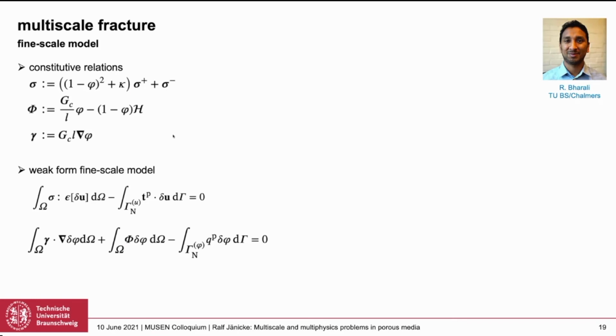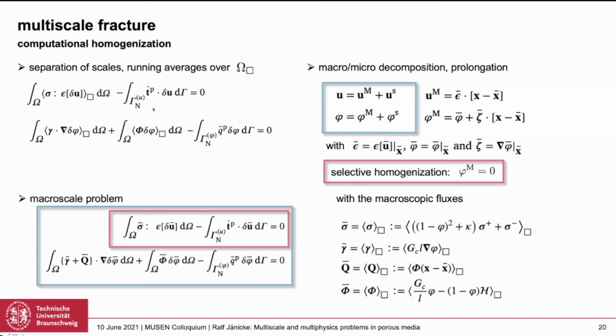So we took our machinery, deriving the weak format and starting all the ingredients, separation of scales with these running averages here. We have this linear type of prolongation, first order in a first order homogenization sense, for the displacement and the damage field, which means that we have a macroscopic damage field and a gradient of the macroscopic damage field, and a macroscopic strain as the macroscopic loading. And just as a side remark, we also considered the case that there is no macroscopic representative for the damage and no macroscopic damage gradient, which means that this macroscopic contribution is simply zero.